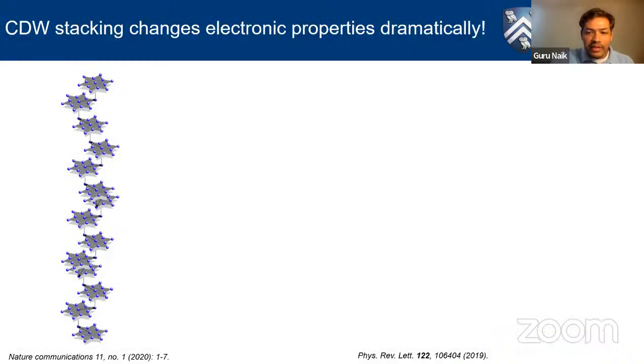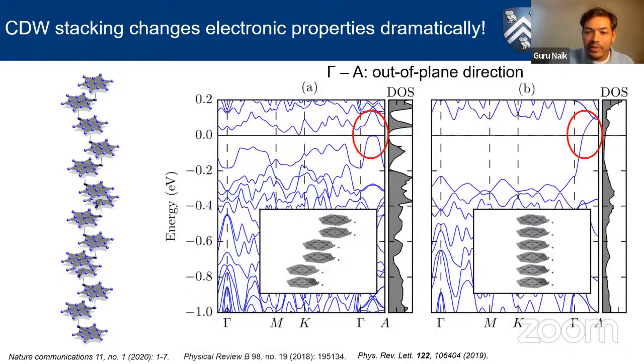About the same time, there were two papers on arXiv which talked about a phenomenon. They said how the CDW domains stack on top of each other. Depending on how they stack, there can be very different electronic properties. That's what these papers said. So for example, let's consider these two layers. This is layer 1 and the upper layer. These are two charge density domains there, the David stars. If they're stacking staggered, not on top of each other, then if we look at their C-axis electronic property, the density of states goes to 0 at the Fermi level. So it is semiconducting.